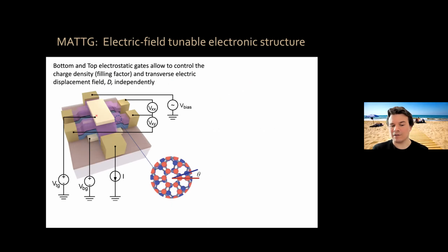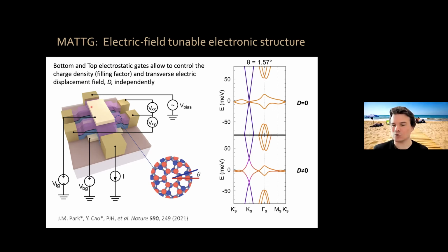It turns out that in one of our devices, we have bottom and top metallic electrodes, so that by applying voltages, we can not only change the charge density, but we can also apply a transverse electric field in the perpendicular direction. That transverse electric field breaks the mirror symmetry of the system and leads to a coupling of this flat band and this massless Dirac band. At finite displacement field, they get hybridized. So we have a knob now with which we can tune the electronic structure of this system, which is something that we could not do with the bilayer case. Now, let me show you that this system is a new robust moiré superconductor.